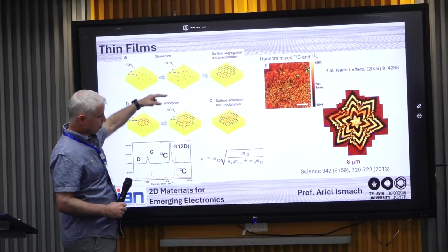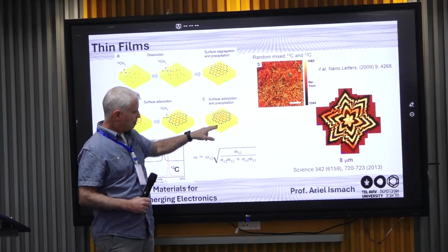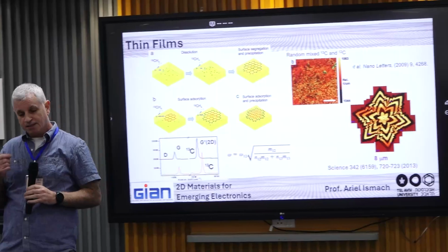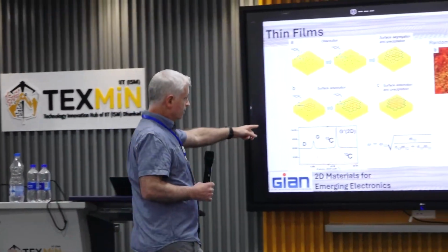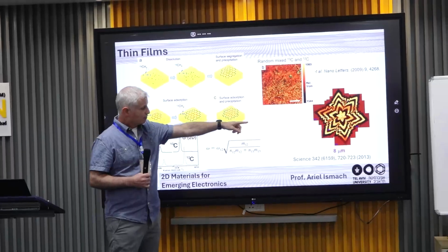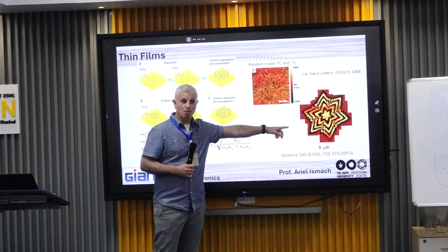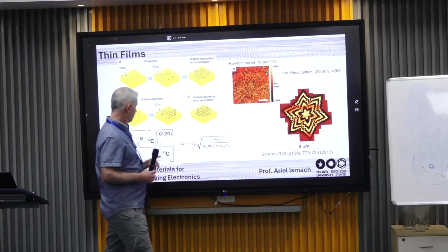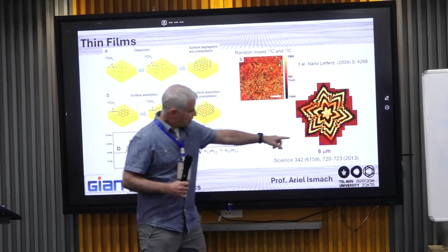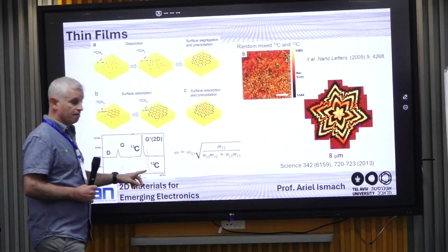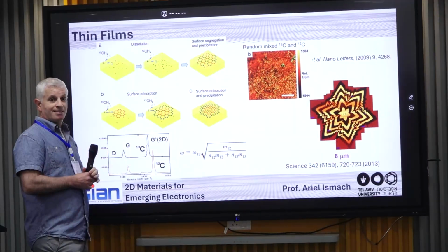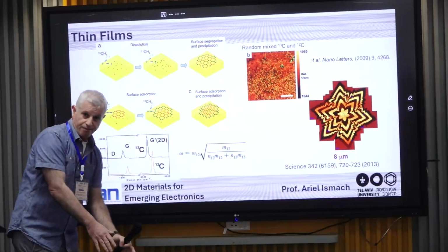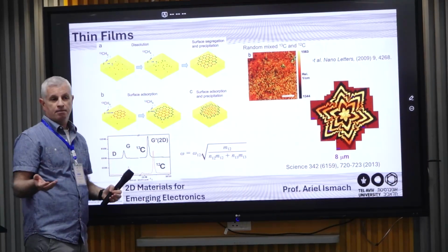What happens in copper is that the growth is surface mediated, so after doing the growth and the mapping, you get this beautiful flower. The dark area here belongs most probably to the C13, and the bright area belongs to the C12, because of the sequential growth. In nickel you don't see that because everything diffuses in and then segregates out together.